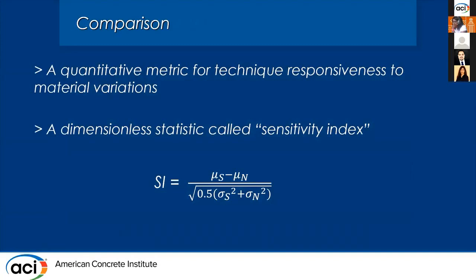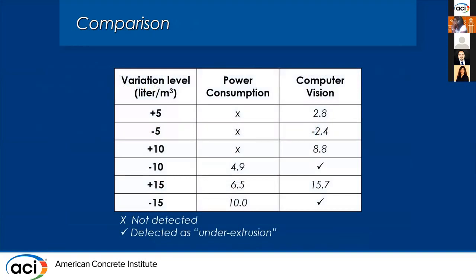And to quantify the responsiveness of each technique against material variations, I used a sensitivity index, which is usually used in other areas to provide the separation between the means of signal and noise distributions compared to the standard deviations of signal and noise distributions. And here you see the values of sensitivity index for each variation level for each technique. As you can see, even at the lowest variation level for computer vision, we have a sensitivity index of 2.8, which means that the changes in the width of the layer are almost 3 times more than the variations in the measurement, which translates into a very reliable detection even at that low variation level. And of course, as the variation level goes higher from 5 to 15, the value of the sensitivity index goes higher, which means even better and easier detection of the variation level.